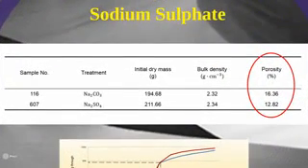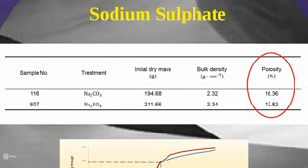Therefore, the largest porosity of the sample for sodium carbonate treatment could retain more salts in its pore space when it was impregnated into the saturated solution, thereby exerting larger pressure against pore walls during the hydration process, causing larger damage. This could also be supported by the final residues produced by sodium carbonate hydration. In contrast, due to the smallest porosity of the sample for sodium sulfate treatment, its weathering efficiency could be hidden.